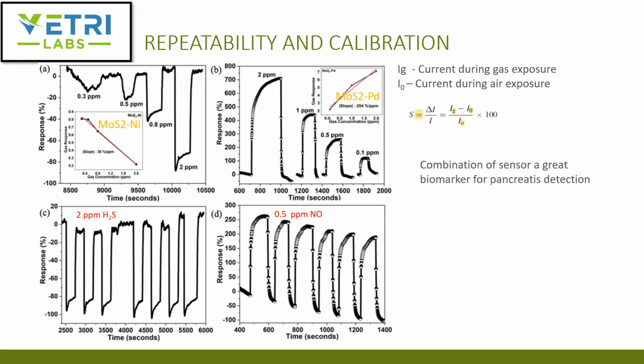And the bottom C and D are just repeatability curves. The C curve is on 2 ppm hydrogen sulfide. It does repeat pretty well when you go back to 2 ppm hydrogen sulfide and then come back to air. It goes back almost to 0. And then on D, there is a drift, as you can see, but it is relatively responding to half a ppm of nitric oxide. So anyway, the combination of these two materials would be a great biomarker for chronic pancreatitis detection. It's a definite clear signal that you can get for the nitric oxide and hydrogen sulfide.